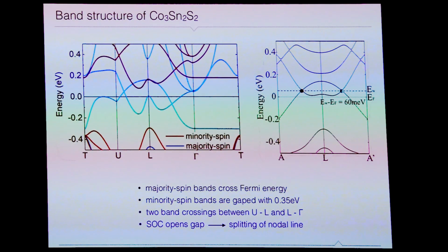And if you cut in another, not arbitrary direction, but not a straightforward direction, you will see there remain two ungapped points. So you have two Weyl points, or a pair of Weyl points. And actually in the Brillouin zone, you will have 3 pairs of Weyl points. And in the beginning, I motivated that such features are related to a large Berry curvature.